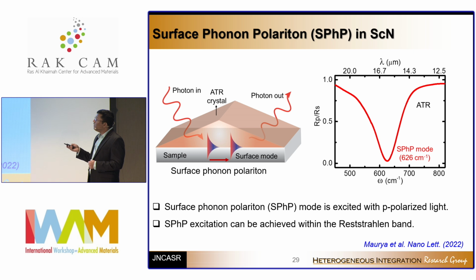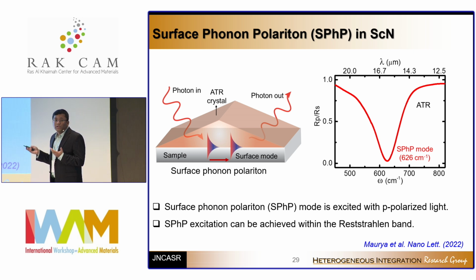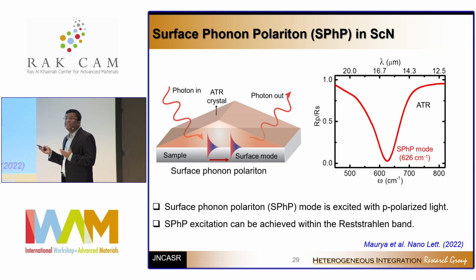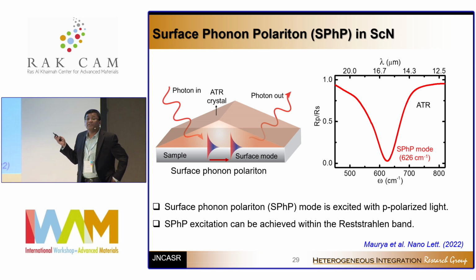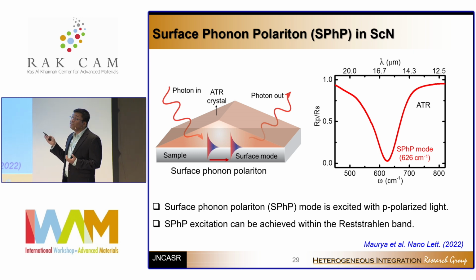of titanium nitride. As I said before, conceptually, theoretically, all of these things are pretty similar, except that the spectral ranges are different. For plasmon-polariton, we could excite it at, say, around 2 micrometer, but for phonon-polariton, we are now exciting at 15, 16 micrometer spectral range.